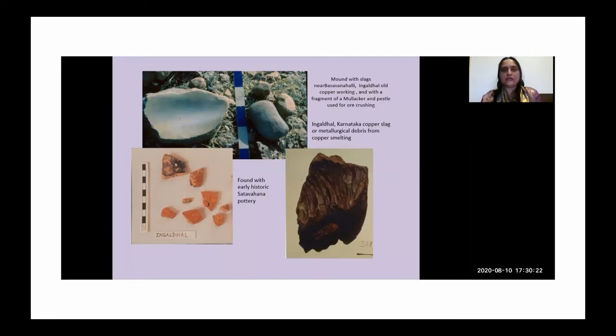some of the waste rocks such as the siliceous quartz and the gangue and other impurities. So when you smelt and reduce the ore from the oxide state to the metal state, then the impurities tend to float to the top of the furnace, and that tends to form a kind of cake which is referred to as the slag. And typically then the metal sinks to the bottom of the furnace where it can be tapped out and such like.